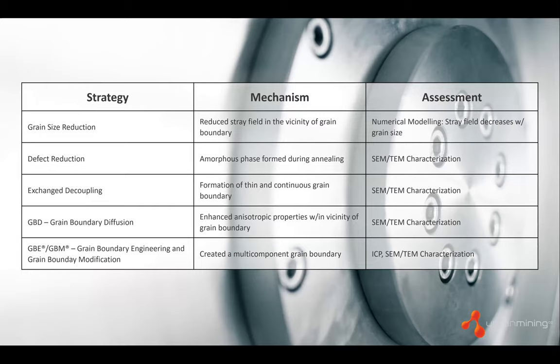So the material adoption in electric motor applications corresponds exactly with this technology development and the strategies employed to improve magnetic properties over time, right? This table is showing the different strategies and mechanisms that were employed to go to the next era of magnet production. When magnets were first invented in 1983, you had an energy product between 20 MGOe and 38 MGOe as the total available commercial range. Then introducing new compositions changed the amorphous phase during annealing, and that gave you a greater than 40 MGOe product without sacrificing remanence.